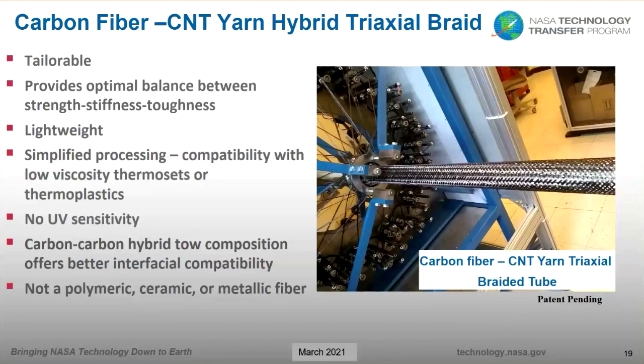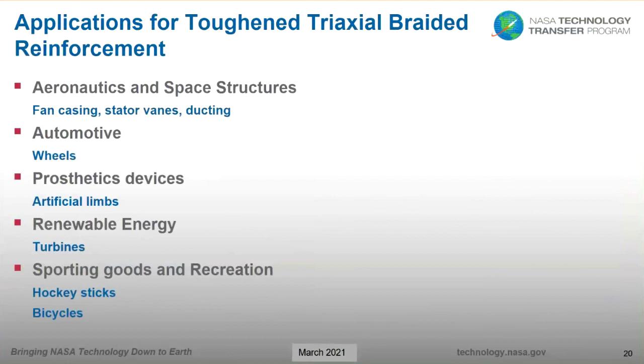In our hybrid material, both fiber constituents pretty much have the same chemical structure, so there should be very little concern over poor interfacial compatibility with using two different fiber materials in the hybrid. And the mechanism of toughness in the carbon nanotube yarn constituent is not contributed to viscoelastic properties of a polymer fiber or what you would see in a polymer. And this material is not a ceramic or metal. It really is in a category by itself.